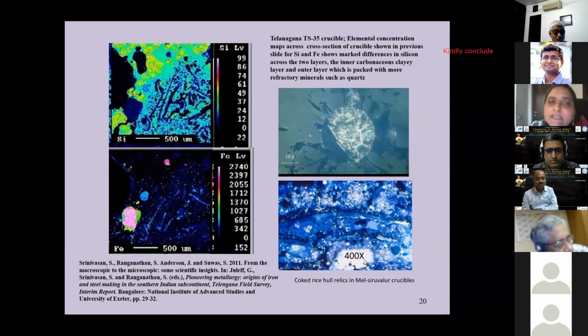And if you see, again, this mix of the inorganic and the organic elements, because when you look at the fabric of the crucible, there are a lot of these additions of the rice hull and so on, which actually was very good in terms of improving the refractory properties, because in this case, the rice hull is very carbonaceous, so it was able to induce this very reducing environment. And yet the outer layer, if you see, that actually has much more of silica. So they were consciously using much more of siliceous materials on the outer layer, because that would make it more refractory, so that it wouldn't melt down when it was heated at high temperatures